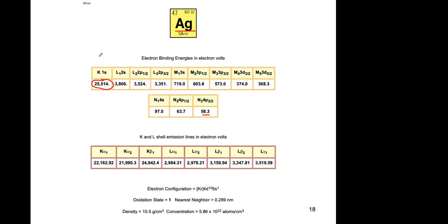Yesterday I mentioned that the difference in energy between the first level and second level is really huge, and here you can see this example. This is 25,000 and this is 3,000, so it's like a 20 kilo electron volt difference between those two levels. Then the second level and the third is probably 3,000 versus 100, and here it's much less. Sometimes you see these level distributions in your textbooks and they are misleading. So just understand that the difference between level one and level two is huge for all the elements, and especially for silver, it's like 20 kilo electron volts.